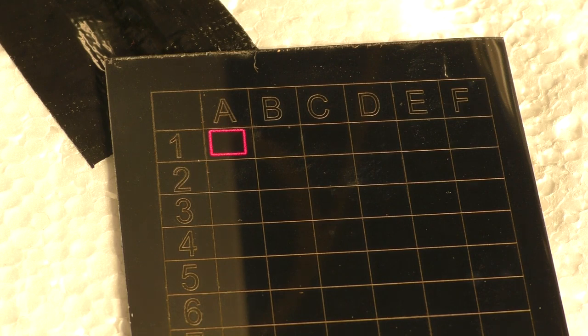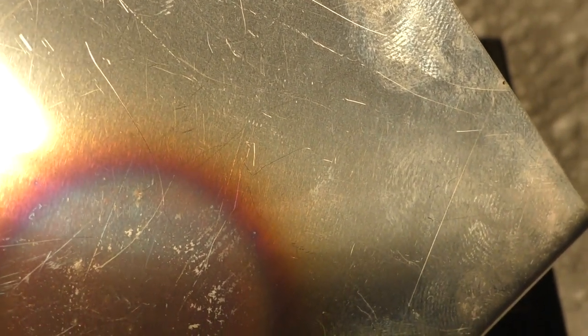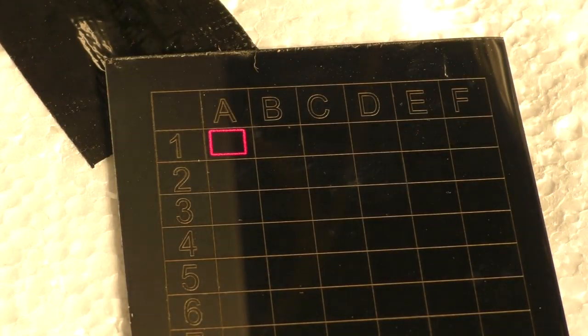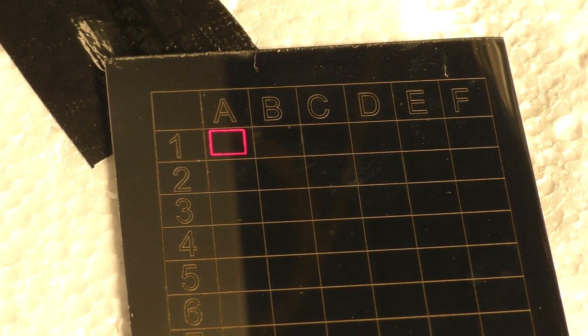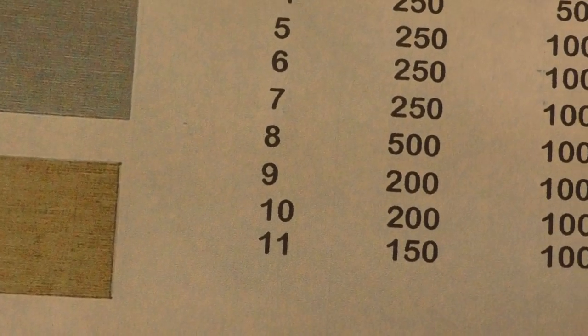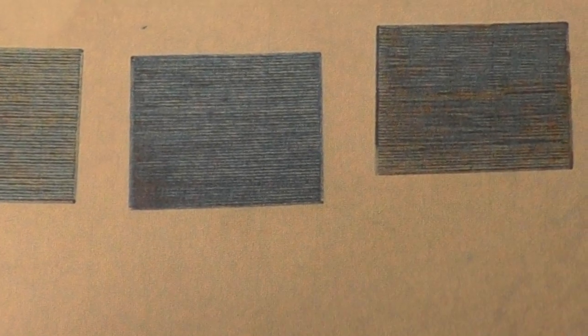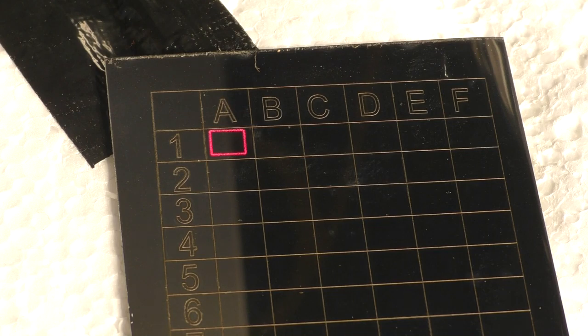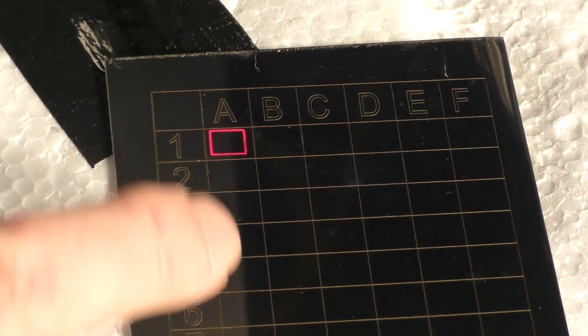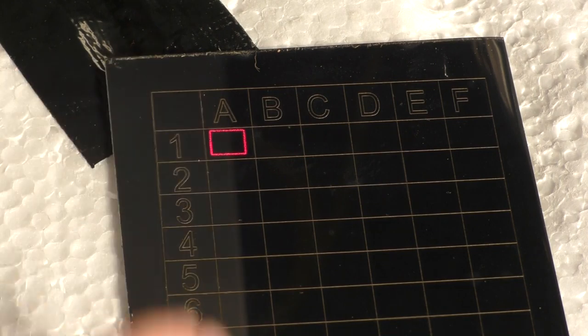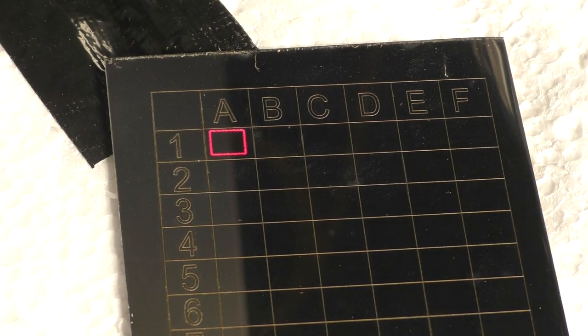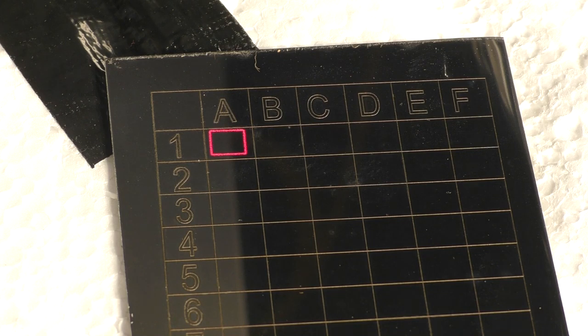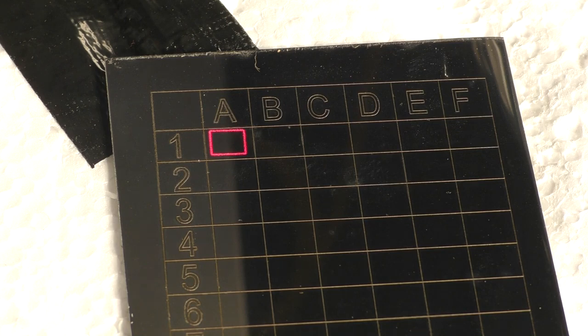So hopefully with the aid of the temperature data, we may be able to home in on some of these colors, because the colors around the outside, the yellows and the browns around the outside, are relatively low temperatures, and the blues in the center are high temperatures. So that would imply that we need to have a fairly high temperature in our scan to produce a blue. So the first test that we're going to do is the gold to blue test. So we'll jump down probably in intervals of 20 millimeters a second to see if we can find a pattern of change in the color. So we do the first one or two just to show you the method and what I'm doing, and then after that I would just plod away on my own and see what I can find, recording the data as I go and then coming back to you from time to time if I can find something that's interesting.